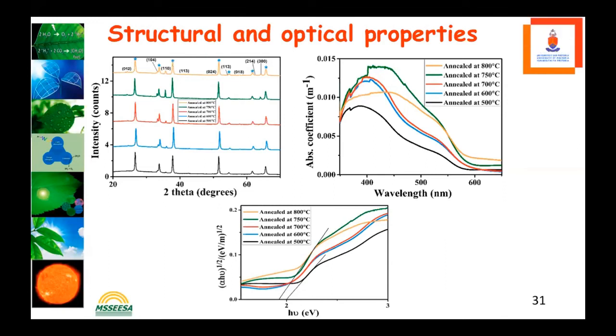The reason behind this is that the material becomes hardened and it starts cracking. The reason why the photocurrent goes down is because after 750, the annealing makes the material hard and it cracks. Therefore, if you think about a cracked material, it is no more compact. Therefore, you cannot measure, the charges are not moving as they ought to.